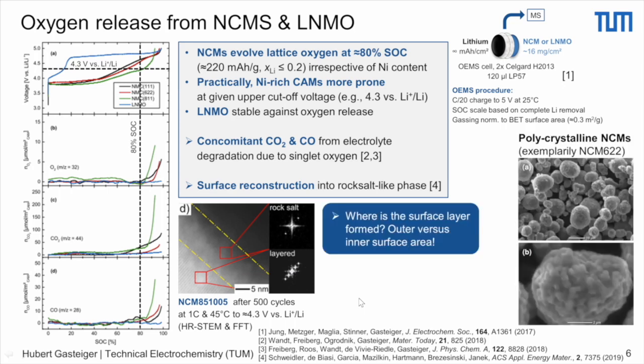Now, when we look at the material morphology, what we know is that these polycrystalline NCMs are actually composed of secondary agglomerates on the order of maybe 5 to 10 micrometers in diameter. And these secondary agglomerates consist of primary crystallites, which are on the order of 0.2 micrometers. So if we measure the BET surface area of these materials, we get about 0.3 meters squared per gram. This is what you would measure. And if you use a spherical approximation, you would calculate an effective particle diameter of about 4 microns.